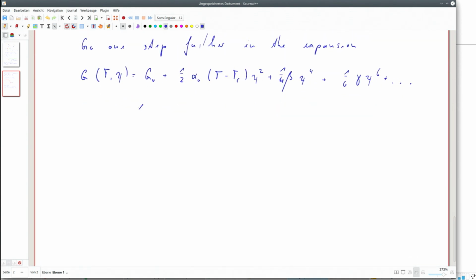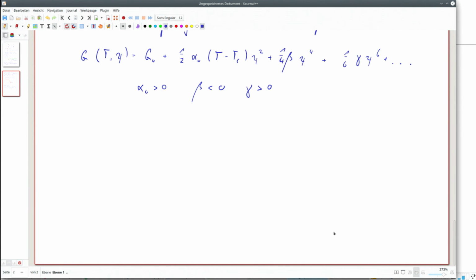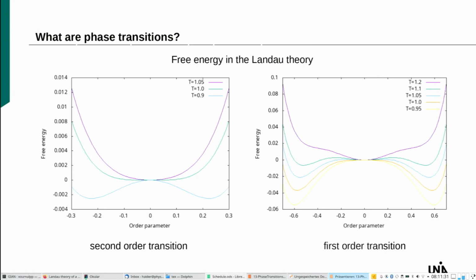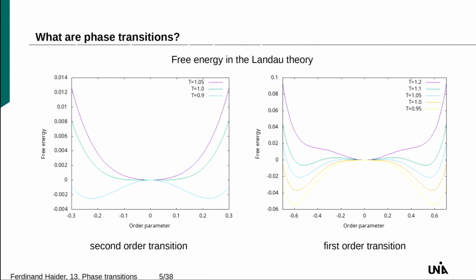As before, alpha 0 has to be positive, but now beta is negative and gamma is positive. And what you obtain then can be seen here. This is for high temperature, at 20% above the critical temperature, these temperatures being multiples of the critical temperature. You find a single minimum here at 0.